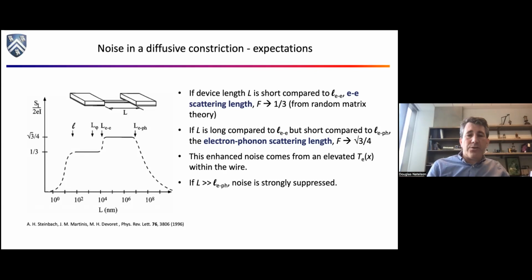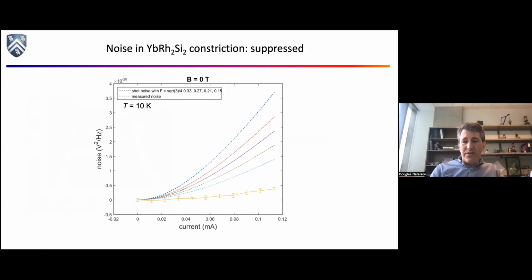All right. So what do you see in one of these constrictions? You don't see this. In the ytterbium rhodium 2 silicon 2, here we are at 10 Kelvin. Here's a bunch of theory curves for √3/4 Fano factor. Here's the 1/3 Fano factor. Here's a couple of other Fano factor values, and here's the data. The stuff is quiet. All right. These wires, unlike the copper oxide superconductor case where the noise was enhanced, here the noise is suppressed well below what you'd expect for single electrons.